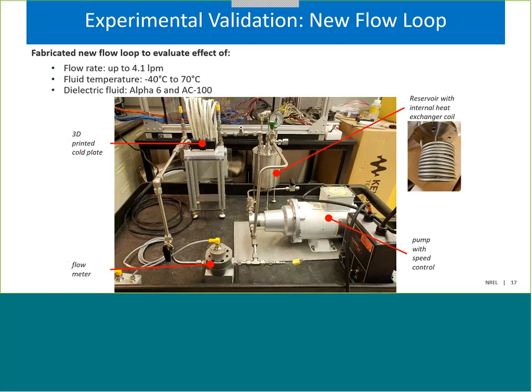And so this is a picture of the dielectric fluid loop that we fabricated to conduct the experiments. You can see the cold plate in the background. The dielectric fluid is stored within the stainless steel reservoir that you see on the back. Within the reservoir, we have a heat exchanger coil that we circulate silicone oil through, and that's how we control the temperature of the dielectric fluid during the experiments. Then we use a gear pump to circulate the fluid. The pump pulls the fluid from the bottom of the reservoir. It circulates it first through a flow meter, and then it goes through the heat exchanger, and then it drains